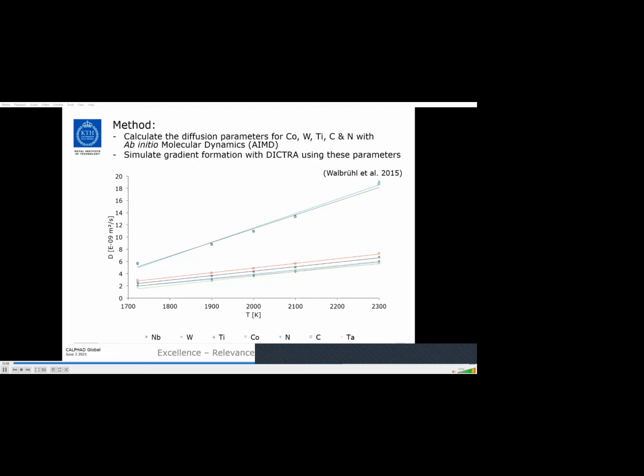So how did we estimate the diffusivities in the liquid binder phase? Well, we used molecular dynamics, ab initio molecular dynamics, and considered the various diffusing elements in the liquid phase. And then those were used to evaluate mobilities, and we could then simulate the gradient formation with the Dictra code. And this was work by Martin Walbrühl a couple of years ago. And here is shown the diffusion coefficient for various alloying elements as a function of temperature.